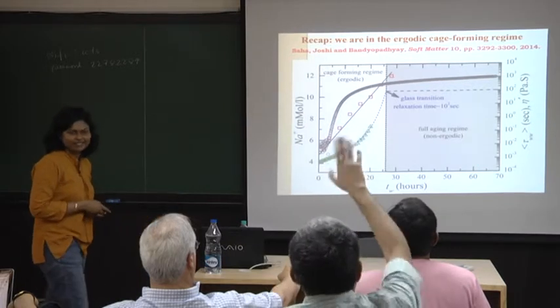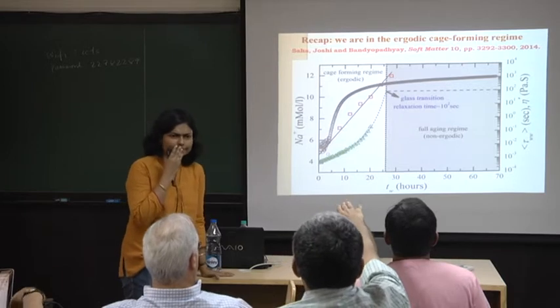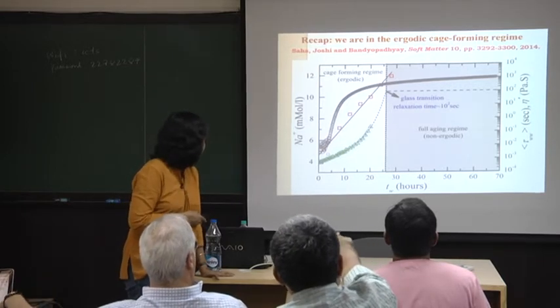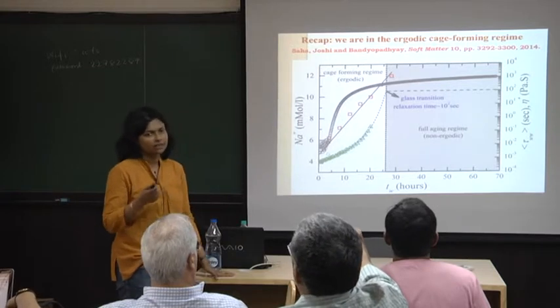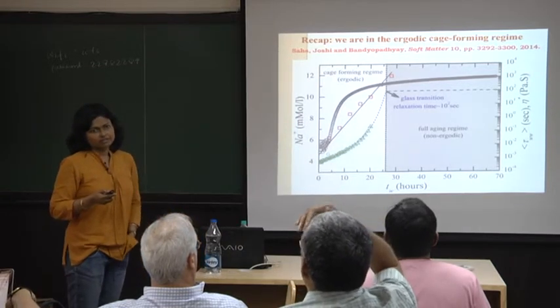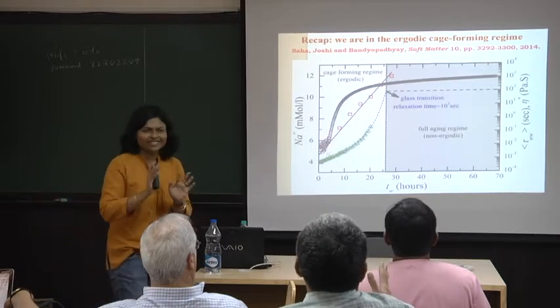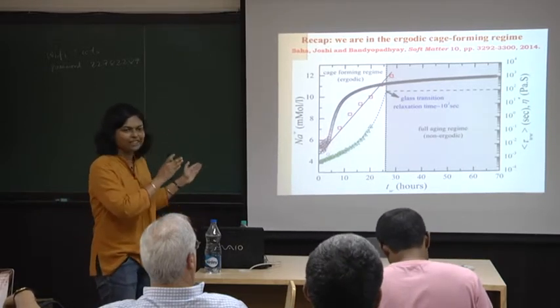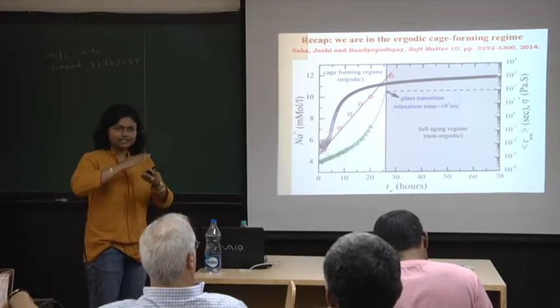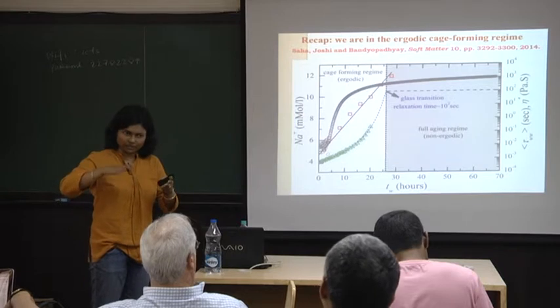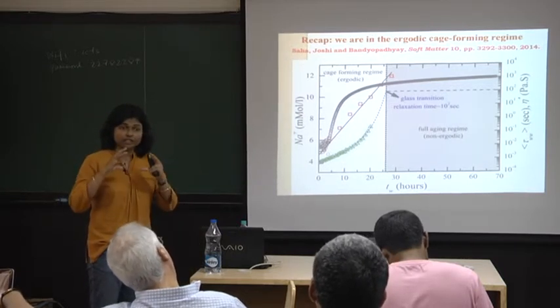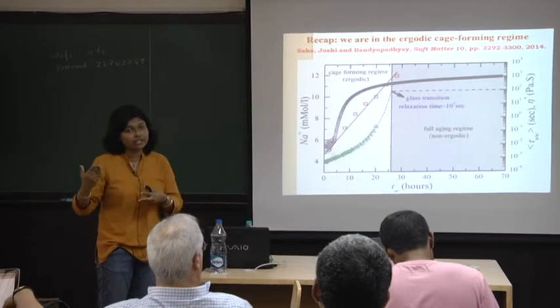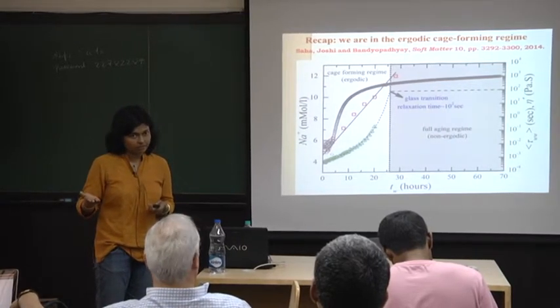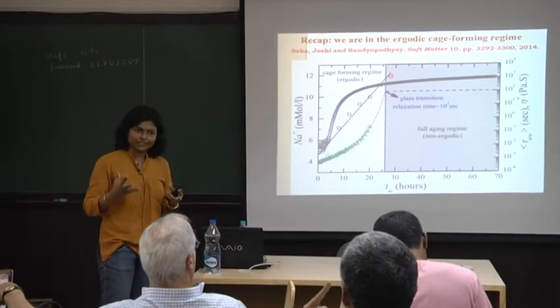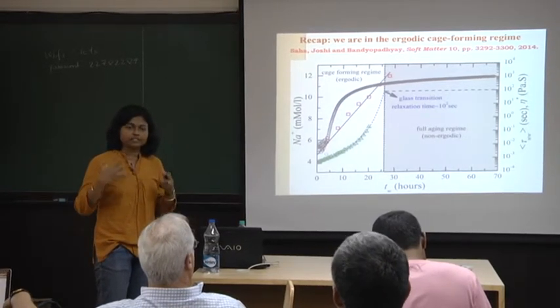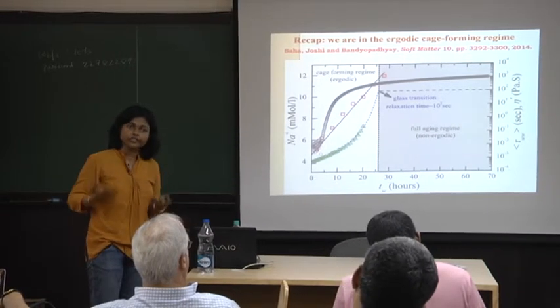Yes, sure. So you said the exfoliation happens really fast, but the sodium ion concentration increases over about 24 hours. It does. I should have discussed the part about the ultrasound data. What we did see is that as the tactoids exfoliate, you have very strong repulsions already in the system that hinder further exfoliation. So the chunk of the exfoliation happens right away, but there's a part of the exfoliation process that goes on for a much longer time.